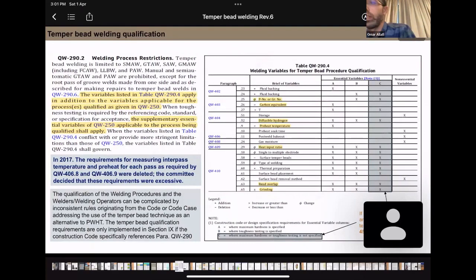So this is the famous table for temper bead, which is QW-290.4. This is where the essential variables are listed. And what I want to emphasize here is that the variables listed in this table apply in addition to the variables applicable for the processes qualified as given in QW-250. What that means is that if you're using SMAW, for example, for temper bead, you have the essential variables and supplementary essential variables in QW-250. Those variables are also applicable. Okay, so not only this table, and I'll show you why this is important.